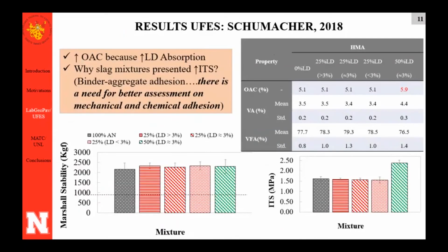Going for the volumetrics, now we took 25% of the net. We did a mixed design with only natural aggregates, and then we took 25% of the natural aggregate and replaced it with slag. The binder content didn't change. Our initial thought would be that we would require more binder, but since we only replaced 25%, it didn't affect the volumetrics.